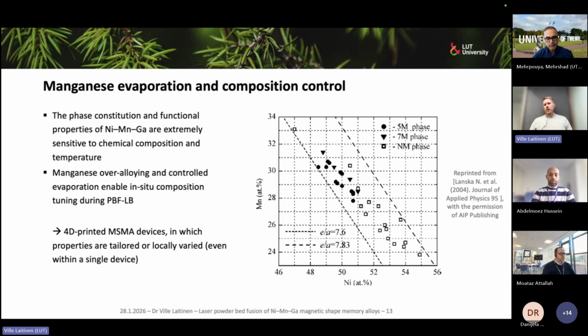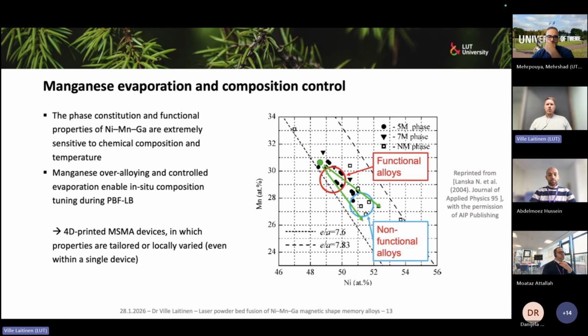Now, this can of course provide a different approach. If we use these over-alloyed powders, we have this on the map. You can see that the functional alloys occupy a very small compositional zone. If we make a powder that is over-alloyed with manganese and under-alloyed with nickel, then with optimal parameters we can achieve functional alloys, and with non-optimal parameters we can, for example, lose excess manganese and achieve non-functional alloys. We have shown that we can use this for tailoring our material. We can do fine tailoring of the martensite transformation temperature, or we can render some zones in the material or final component completely inactive.